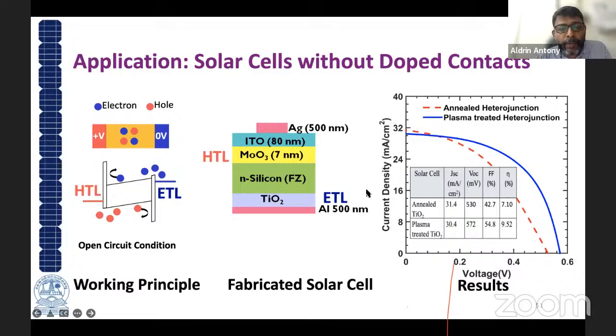And so this is a solar cell we fabricated. On one side, we put a MoO3 of 7 nanometers, that's a hole selective layer. And on the other side, we put an ETL, that is titanium dioxide. So when this solar cell is fabricated, we could reach a solar cell efficiency of something around 9.52%. That is a heterojunction solar cell with both sides without any dopants. We are just using an evaporated moly oxide and ALD deposited titanium dioxide on the other side, and a metal on the one side, the back side, and ITO on the top as an anti-reflection coating and as a front contact, and then with a metal grid.